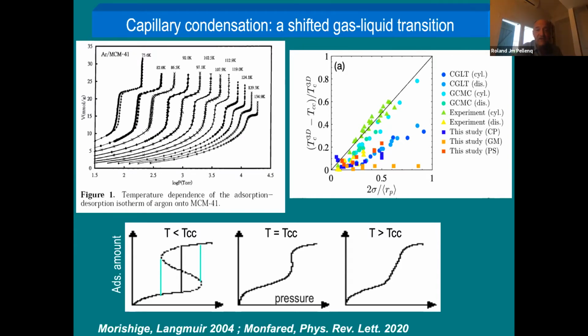Even in these bigger pores you can still have a phase transition. The plot on the left is recent work we published, the PhD of Siavash Monfared, who's now at Caltech, was with us at MIT—this shows the shift of the critical point of the confined fluid, because the confined fluid, although experiencing a phase transition, is not the bulk one. There's a new critical point due to confinement—again showing that confinement and interaction shift things.